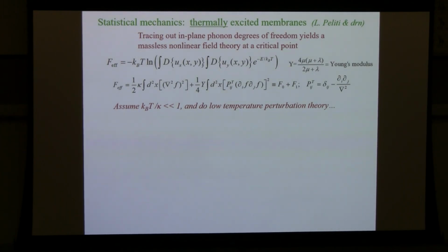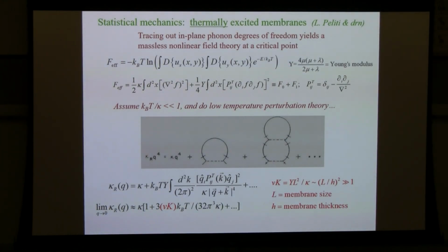If I have an undulation like that corresponding to a longitudinal phonon, there's a typical soft restoring force. But if you try to go this way, you have to tear the surface. And so the Young's modulus comes in, and that's ultimately what leads to some of the interesting science that I'll talk about. To see that there's interesting science, what we can do is just imagine we're not at zero temperature, but close to zero temperature, and assume that k_B T over kappa is small, so bending rigidity is large compared to temperature. Just do perturbation theory. Here are some Feynman diagrams that come from expanding this quartic coupling, and you can get a renormalized bending rigidity, something Luca Peliti and I did quite a while ago. And if you look at it, there's a correction to the zero temperature bending rigidity.